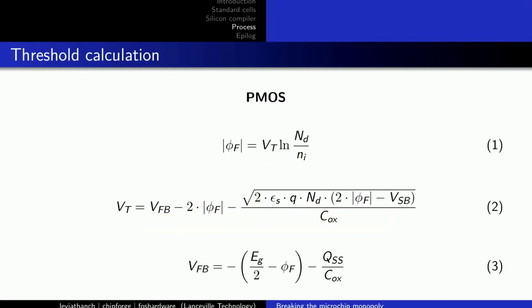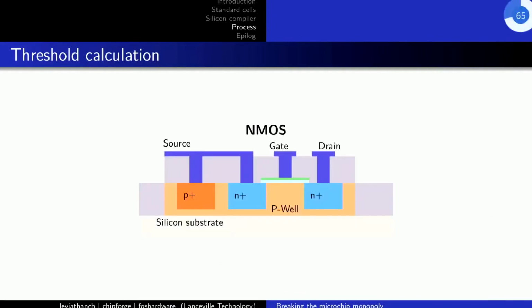What essentially controls the threshold voltage, so the operation voltage, which in standard CMOS is usually around 0.8, respectively minus 0.8, is the doping here, like the donors, respectively acceptors. And the QSS, that's the oxide charge, is usually a process-specific constant, but it can change.